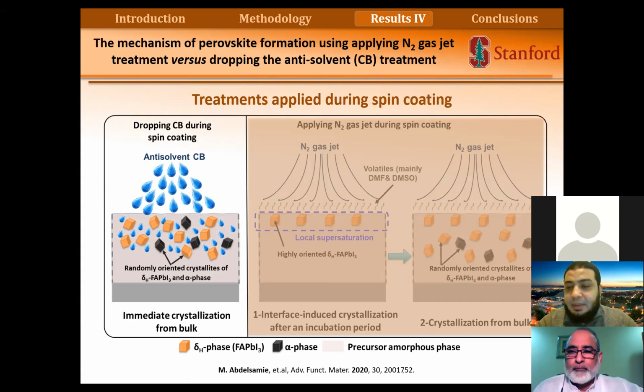I think it's also related to the intermediates. The DMF itself, when it forms intermediates, forms very large fibrils of the intermediate, and this kind of intermediate gives lower quality of the film at the end after thermal annealing. But with DMSO, it forms the intermediate itself. It doesn't have these large fibril structures. So DMSO forms a more uniform film that also gives a much smoother film. So that choice of solvent has a large effect on the final product. I think the community was initially using DMF, but they found it's not giving the appropriate properties, so they tried to add some DMSO into it.